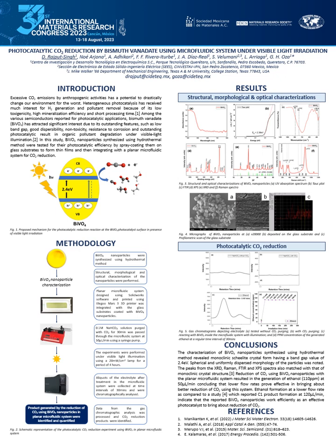The experiment was performed using 0.1 molar bicarbonate solution, which was allowed to pass through the microfluidic cell at a rate of 50 microliters per minute with the help of a syringe pump under visible light illumination, and the aliquots were taken at a time interval of 30 minutes, and finally the entire experiment was run for a period of 4 hours. Eventually the product generation and identification was tested using gas chromatographic studies.